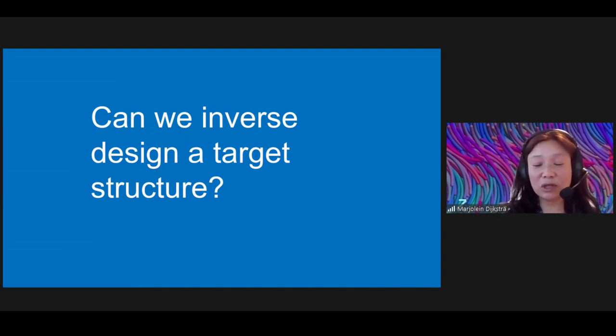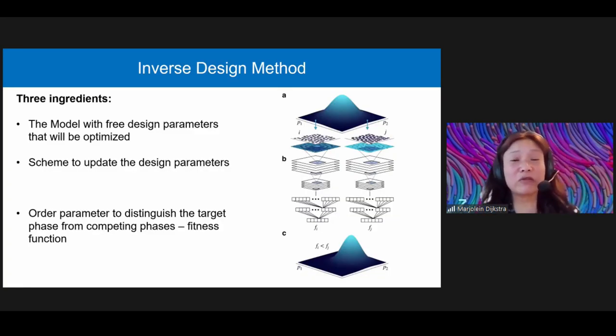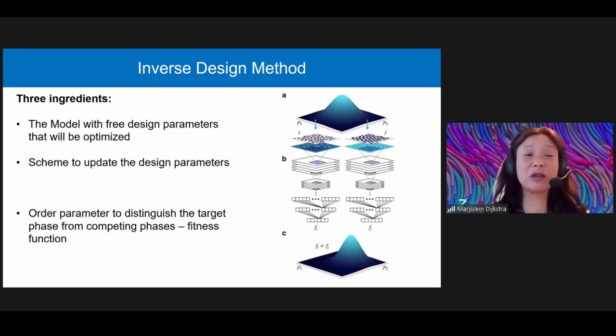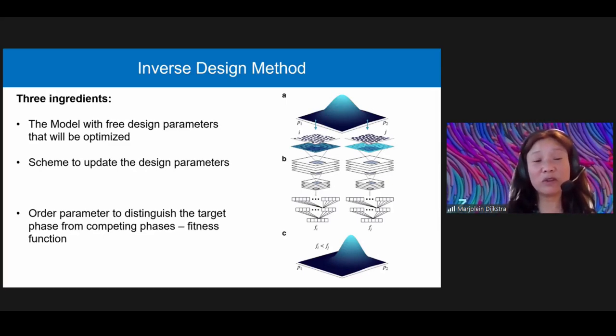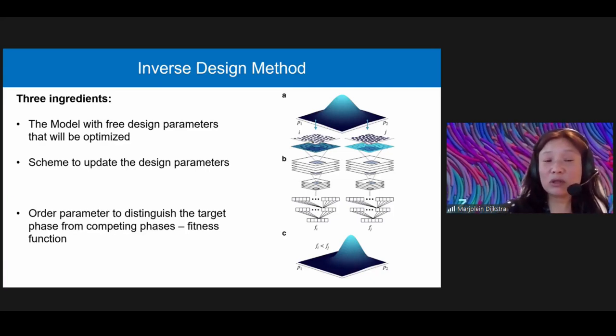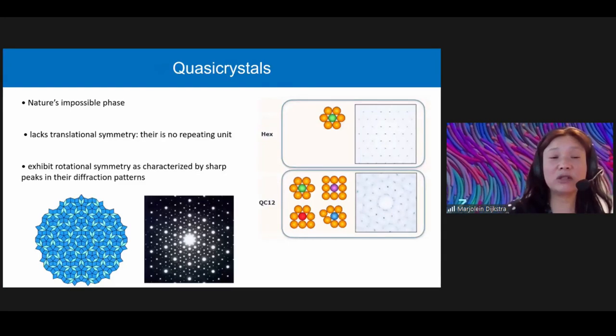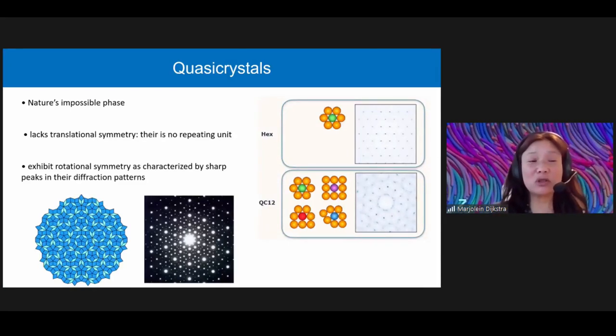So that's the question that we would like to address here. So an inverse design method consists basically of three ingredients. We first need a model with design parameters that we can optimize. We then need a scheme to update the design parameters, and then we need an order parameter that is able to distinguish the target phase from all the competing phases and can be used as a fitness function for the design update scheme. So the model that we use is a model that gives rise to quasi-crystals. Quasi-crystals are also regarded as nature's impossible phase. It lacks translational symmetry. There are no repeating units.